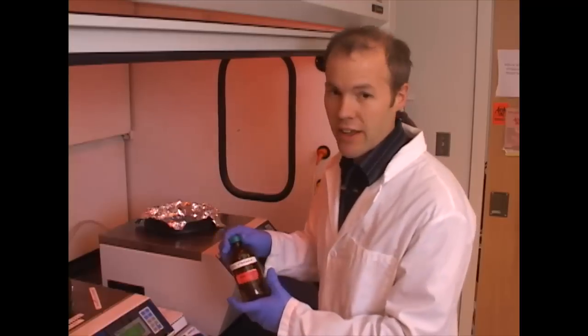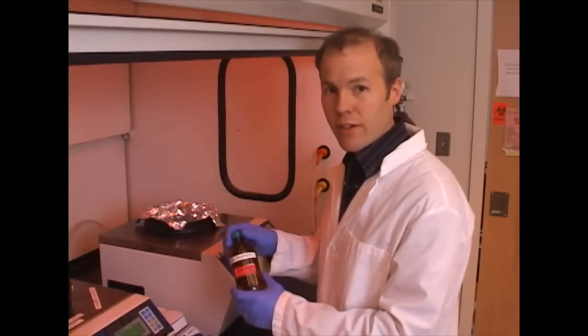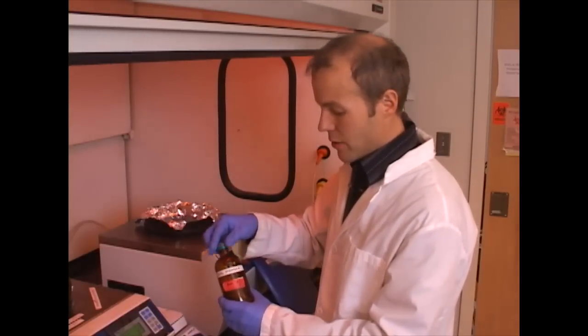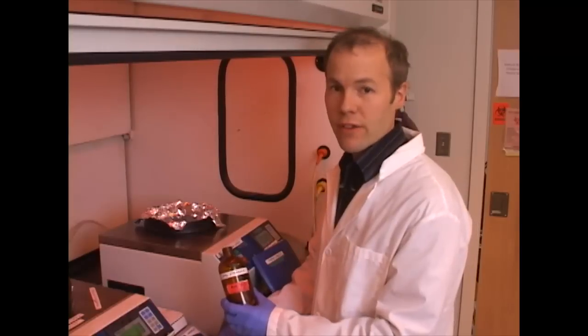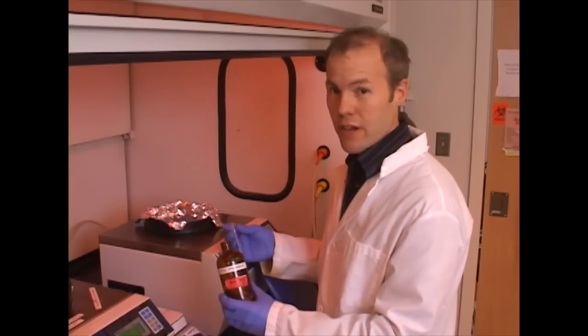In this case, we're using a 3% polymethylmethacrylate resist. The resulting layer for spinning this at 4,000 RPM should be about 300 nanometers.